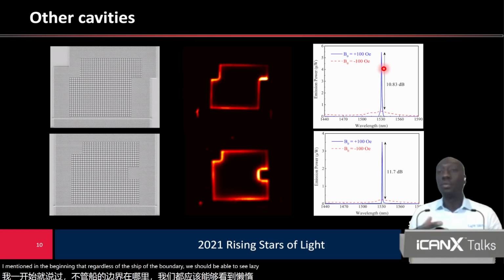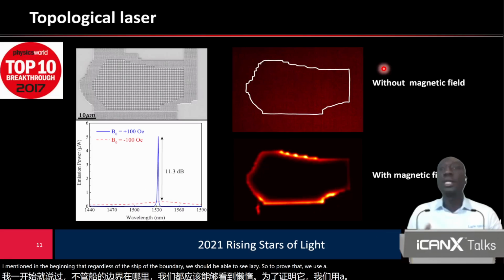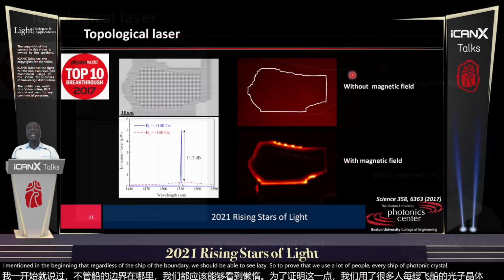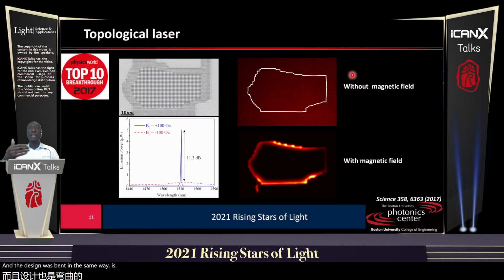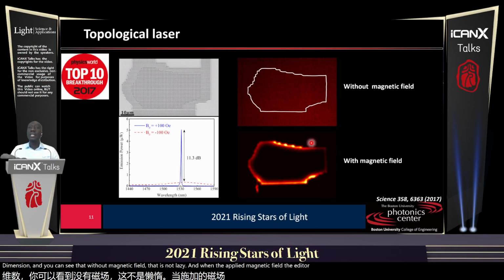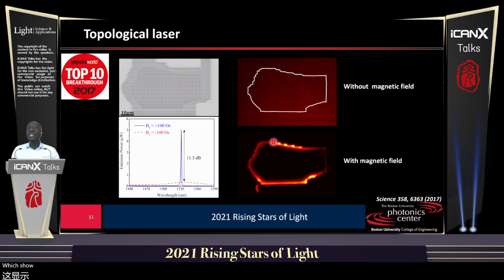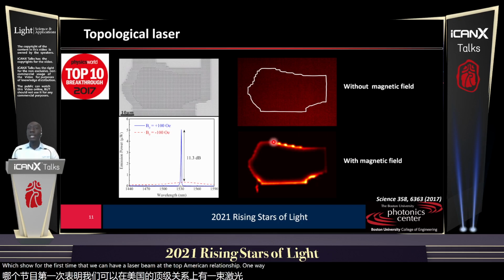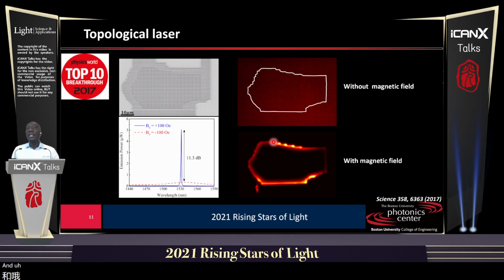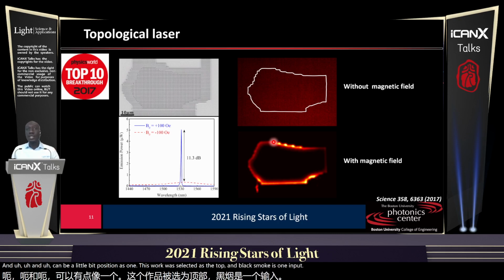I mentioned in the beginning that regardless of the shape of the boundary, we should be able to see lasing. To prove that, we used an arbitrary shape of photonic crystal, and the design was done in the same way, with the same band diagram and the same dimensions. You can see that without a magnetic field, there is no lasing, and when you apply a magnetic field, the edge state is very well defined, which shows for the first time that we can have a laser with one-way propagation and an arbitrary shape as well. This work was selected as one of the top 10 breakthroughs in physics in 2017.